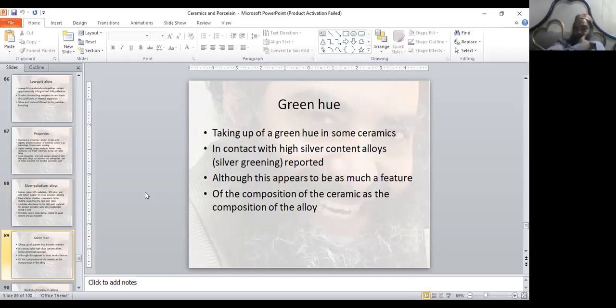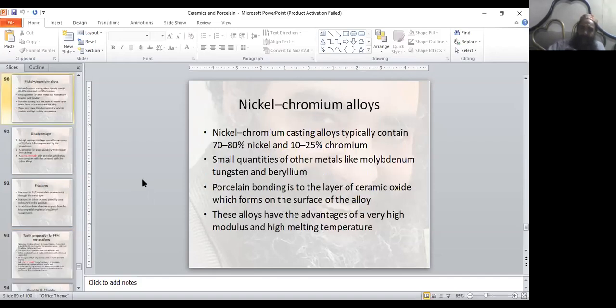A green hue due to the silver taking up of a green hue in some ceramics. Ceramic may take green color from the silver. In contact with high silver content alloy, silver greening is reported. So the green hue is silver greening. Although this appears to be as much a feature of the composition of ceramic as the composition of the alloy.